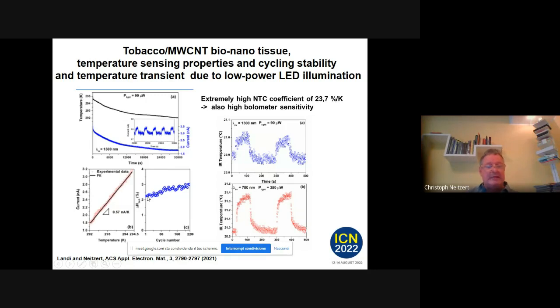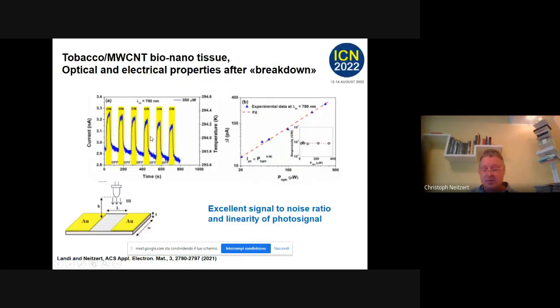The change should be due to some characteristics of the gap. No, here we measure the temperature with an infrared thermometer without and with illumination, and actually we see that the change is just 0.1 degree, and here is 0.3 degree, for 1300 nanometer as before, and here is for 780 nanometer. So it's 0.3 degree, and you see a very nice signal for this 0.3 degree.